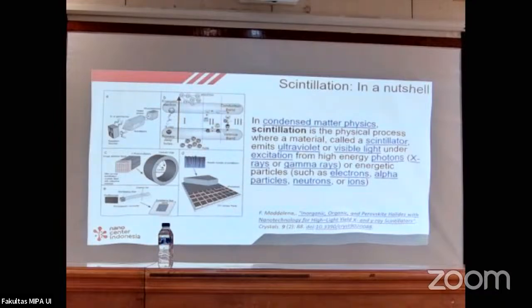Compared to the 3D bulk system, in Toby's paper, for example, we try to demonstrate and compare 0D all-inorganic copper perovskite to the 1D. It turns out that if you go too low in terms of dimension, you actually make things worse, because the charge carrier dynamics are not so promising for a scintillator, where everything has to go very fast. If you can go into the regime of picoseconds, then we are in the game. That's the nice thing with perovskite: when you change the structure or the dimension, you can manipulate the charge dynamic profile of the system.